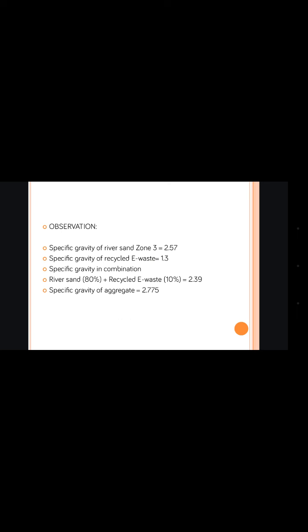The specific gravity tests were carried out, and as per IS 2386 part 3 of 1963, the nominal specific gravity of fine aggregates used in concrete ranges from 2.4 to 2.6. The specific gravity is also determined for coarse aggregates separately for 20 mm and 12.5 mm. As per the observations from the tests, we found the specific gravity of river sand is 2.57. To be noted, it's zone 3. For e-waste, it's 1.3. The combination is 2.39 and the specific gravity of aggregate is 2.775.